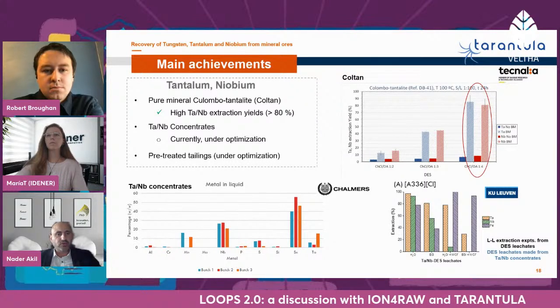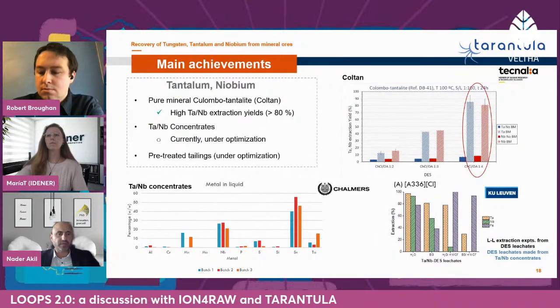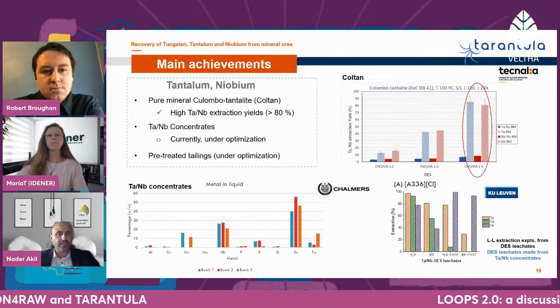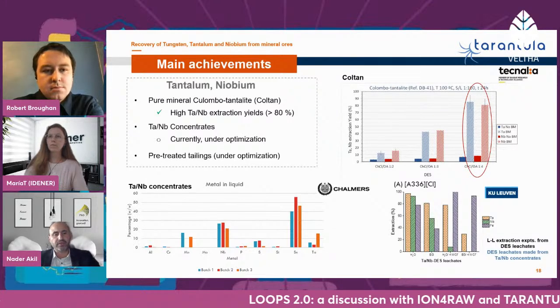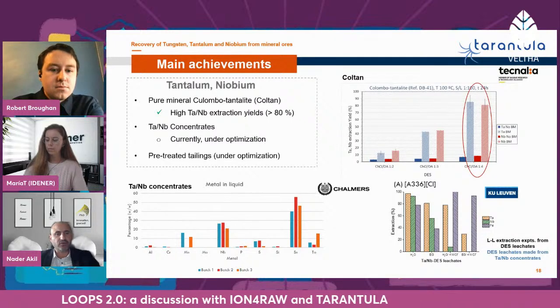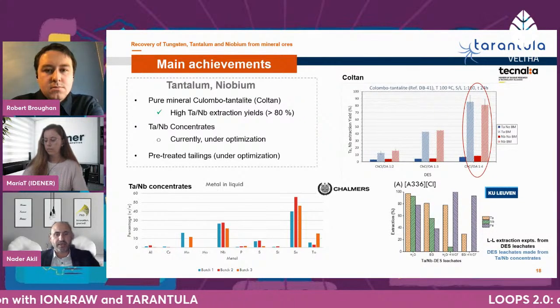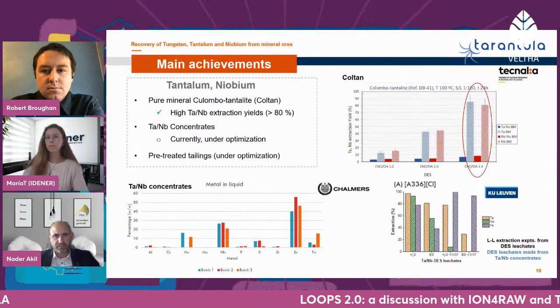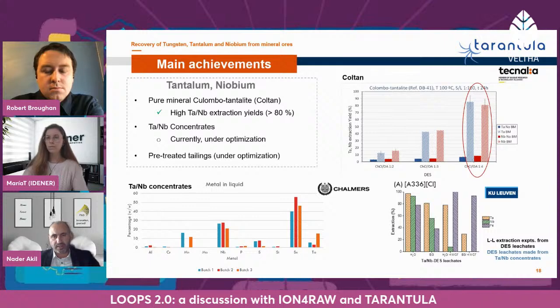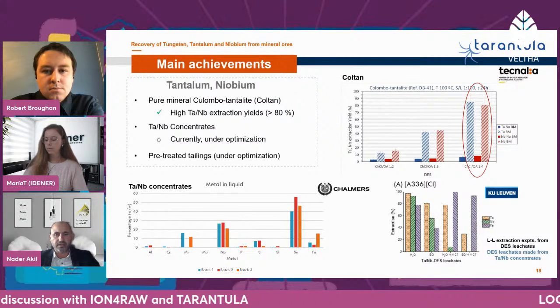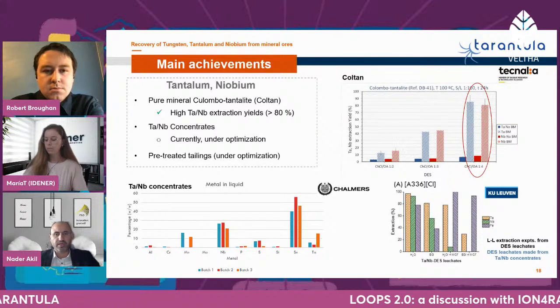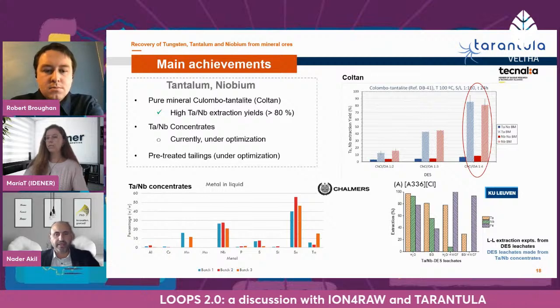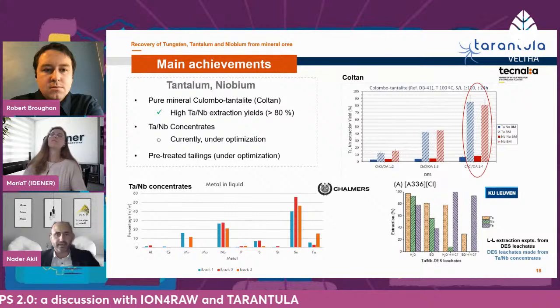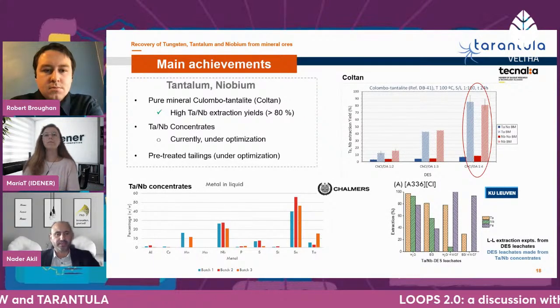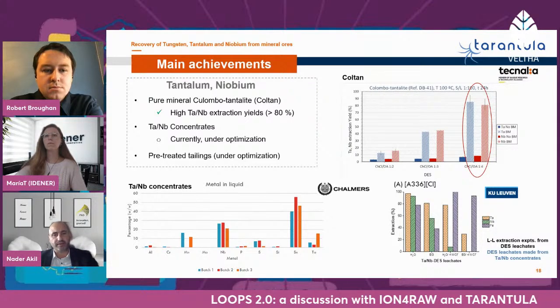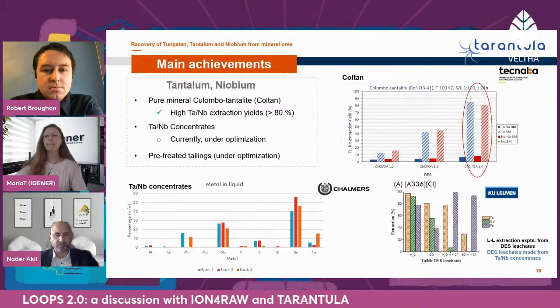As for the tantalum and niobium, so far we have some results on pure mineral, the coltan, the columbo-tantalite material, where we have achieved high tantalum and niobium extraction yields, more than 80%, as can be seen here, for instance, with the process of Tecnalia. It shows a high yield, and with some parameters, for instance, when we use ball milling or we don't use ball milling, it shows a huge difference in the leachability, basically because the ball milling makes it easier for the leaching to be processed.